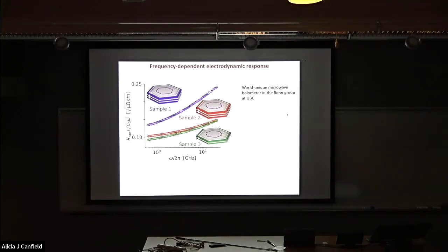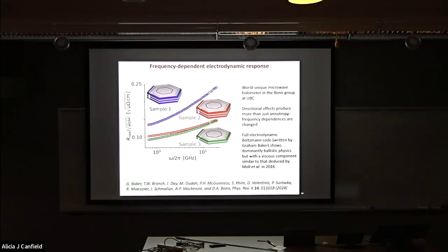Recently we published, earlier this year, the work that Graham Baker and Doug Bonn did, where they used this world unique bolometer that they have at UBC, and studied the frequency dependence of the microwave conductivity over a decade and a half of frequency. What they saw was that depending on the angle that they cut their samples and set their currents going around compared to the Fermi surface, not only did they have a numerical anisotropy, which people had expected, they also had an anisotropy that changed the power laws they were seeing of the frequency dependent conductivity. And that we hadn't anticipated.